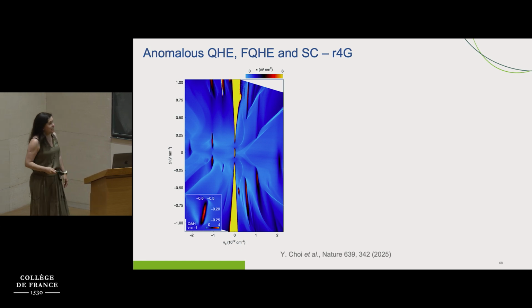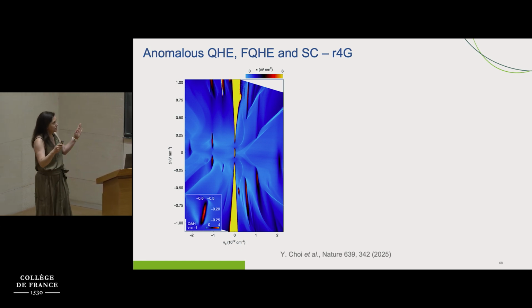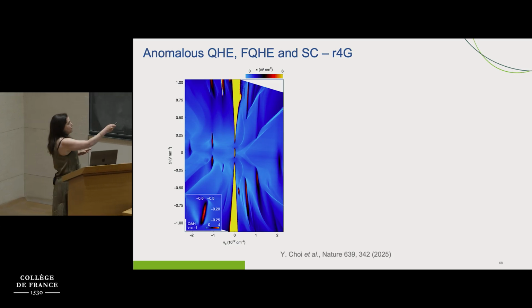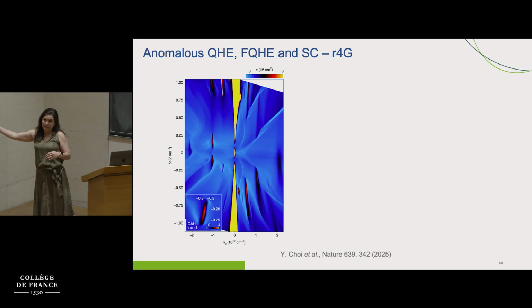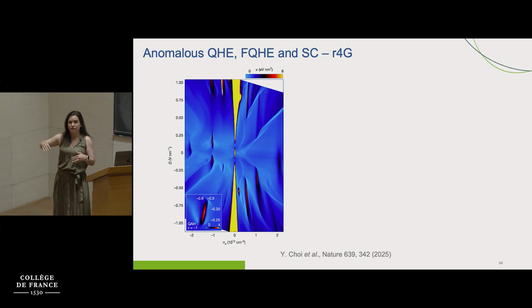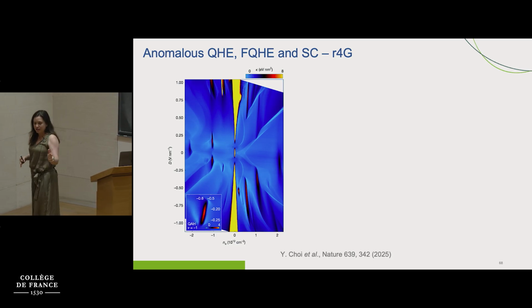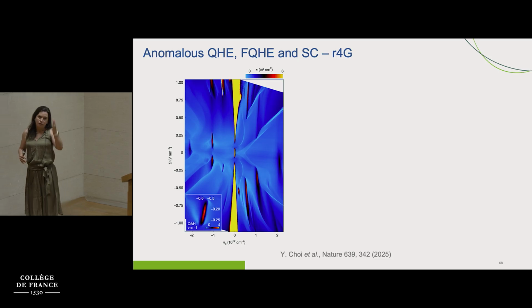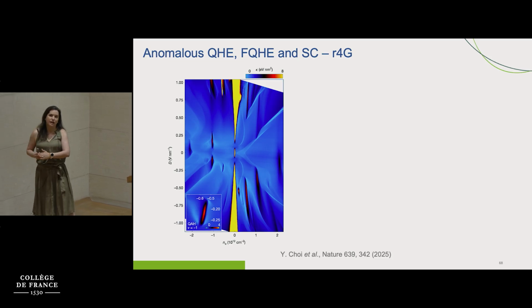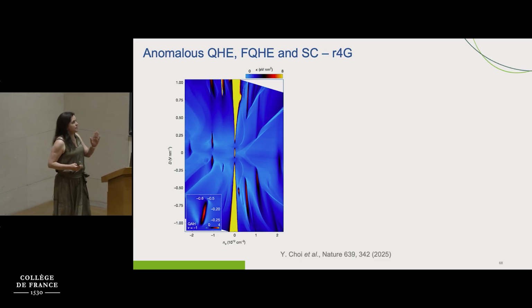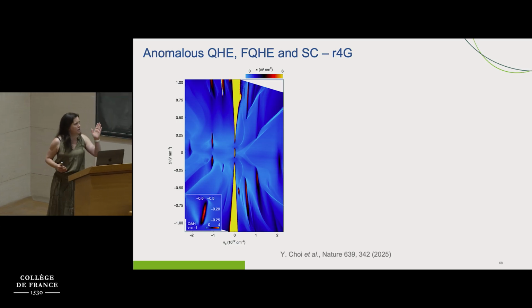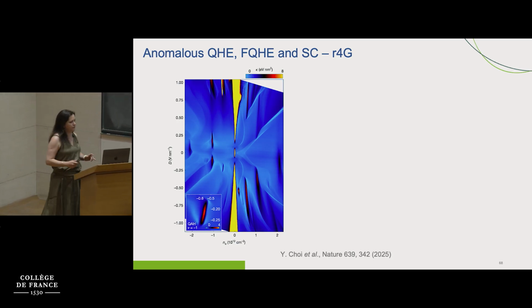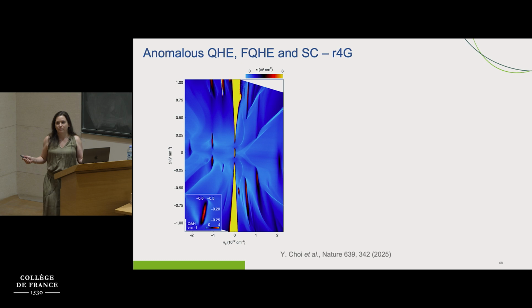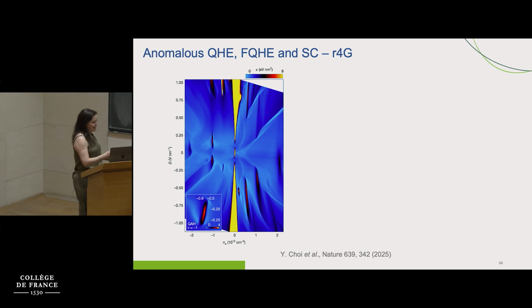And in fact, just to give you an overview, now we're going to change the number of layers. We're going to go from the pentalayer that we were working with before to 4 layers. By the way, these topological effects have been observed in 4, 5, 6, and 7 layers. Superconductivity has been observed in 3, 4, 5 layers only. Unless someone published a paper this morning that I'm not aware of, but I'm going to try to read it when I go back home.